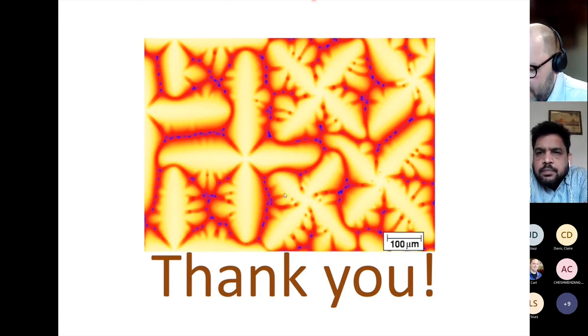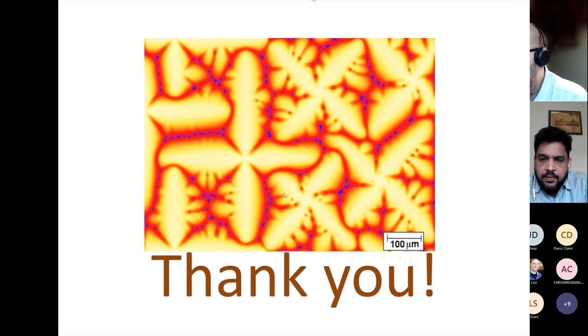In the standard phase field model that I presented, where I showed all of the examples, that one had been using the parallel tangents. The approach I presented towards the end has not been using parallel tangents, but instead simply using the actual chemical potential to drive the flux of atoms across the interface. So during the non-equilibrium modeling, we don't do parallel tangents anymore. I want to get away from parallel tangents for a number of reasons. So we stopped that local equilibrium assumption.